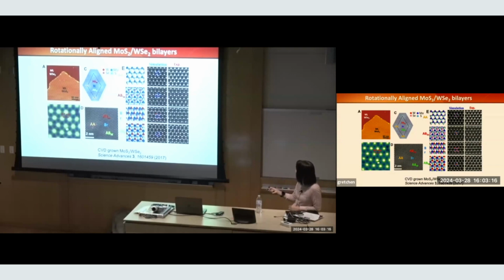I can look at one location that's A stacking. I'm just going to use the terminology. It means the top hexagon is perfectly on top of the bottom hexagon. You move over by a few unit cells, and now one of the atoms sticks out in the top layer hexagon center. So then you will have these few high symmetry points that maintain the threefold rotational symmetry. These high symmetry points tend to be the energy minima in the Moiré potentials, where a lot of things are happening. So this is a picture of topology. The layer spacing is actually gradually changing.